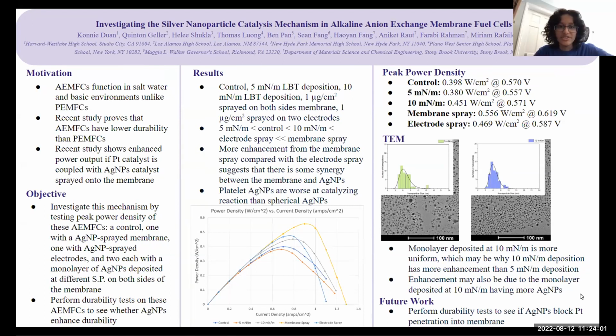The TEM images and size distribution graphs we generated of silver nanoparticles show that the monolayer deposited at 5 millinewtons per meter surface pressure has a higher size distribution, and some of the nanoparticles appear to be platelet shaped. The monolayer deposited at 10 millinewtons per meter surface pressure is more uniform with a lower size distribution, which may be the reason for producing a higher power density, but that could also be attributed to the fact that there were simply more nanoparticles at the 10 millinewtons per meter surface pressure deposited monolayer.